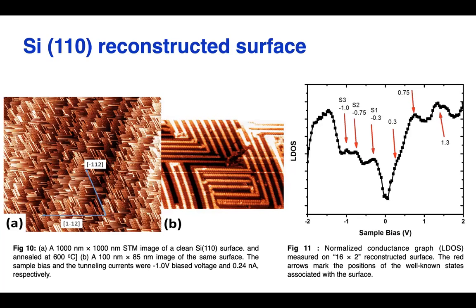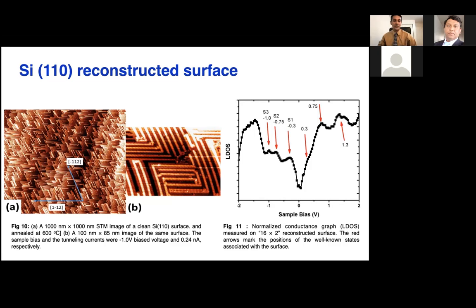This arrow shows the high symmetry direction on the surface. You can see this zigzag reconstructed surface. It has a well-known structure we call the 16x2 structure, like silicon 111 has the 7 by 7 structure. The well-accepted structure for the reconstructed silicon 110 surface is the 16x2 structure. But we are still not sure we got this reconstructed surface until we perform electronic property studies. Otherwise, we cannot predict that we have the correct reconstructed surface.